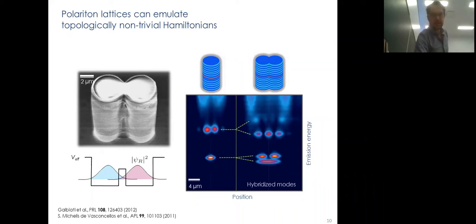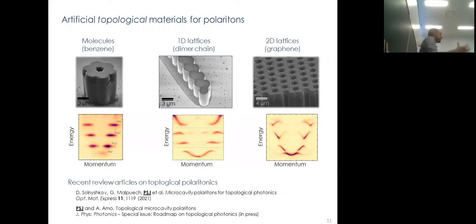What I'm showing here on the right is the case for a single atom, and when we couple them together, we see that they hybridize. For example, the ground state will form a bonding mode that is symmetric and an anti-bonding mode that is anti-symmetric, and all the orbitals will couple to each other. So what we can do eventually is couple more and more of these pillars and form artificial materials. On the left here, we have a system consisting of a benzene-like molecule, a hexagonal shape of distinct micropillars, and we see that we have a set of discrete eigenstates that are reminiscent of the benzene electronic states.